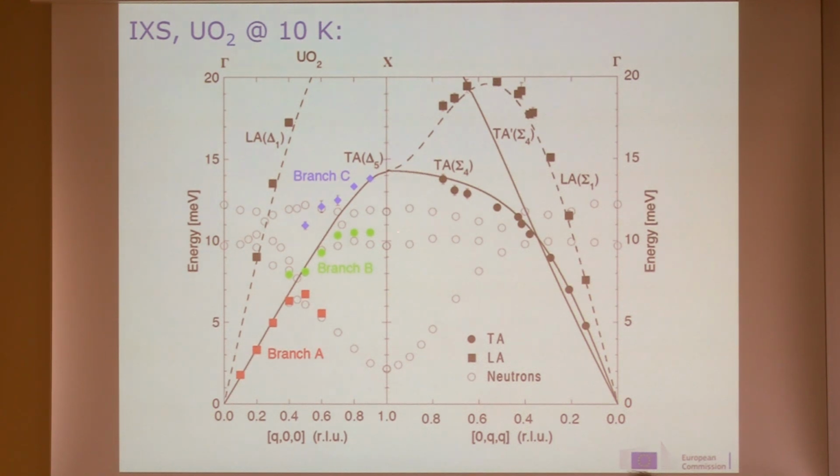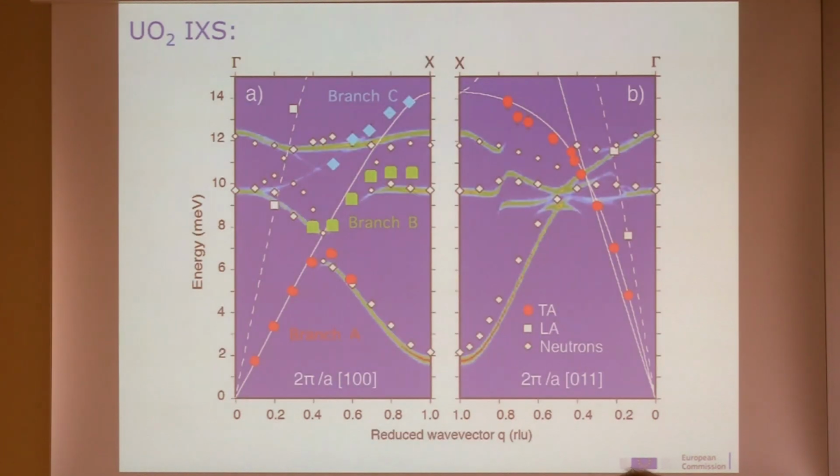The open points are the magnetic intensities measured by neutron scattering. So what you can observe with these two techniques are the magnetic component of the mixed mode with neutrons, and the phonon components of the mixed mode with inelastic X-ray scattering. Then you can also measure the phonons with X-rays. And you see in particular that we see no splitting along the 1-1-0 direction.